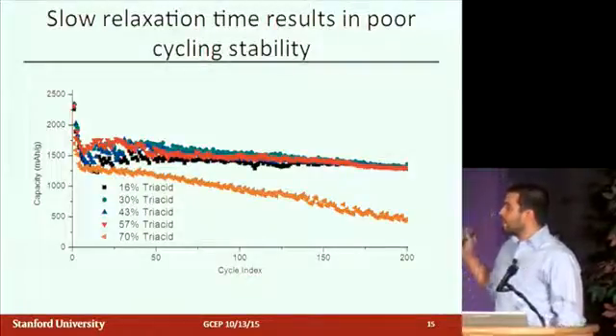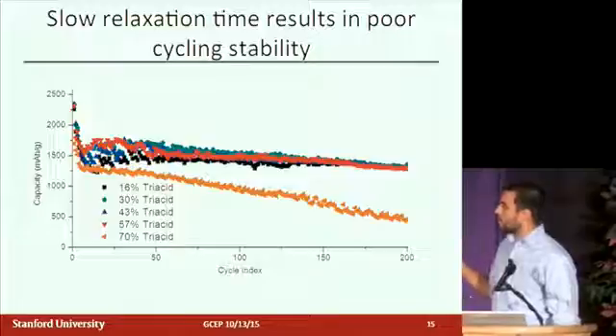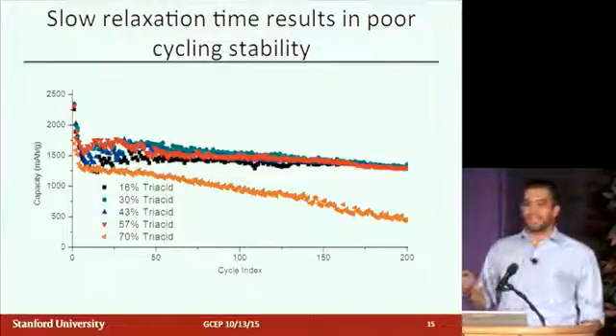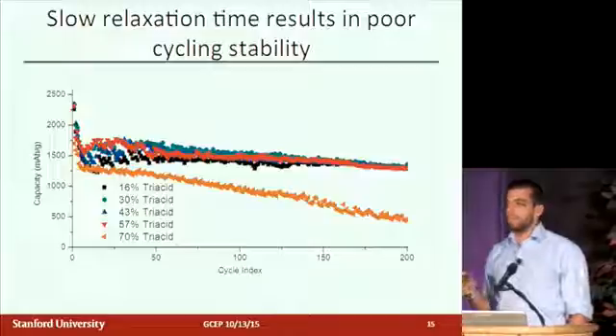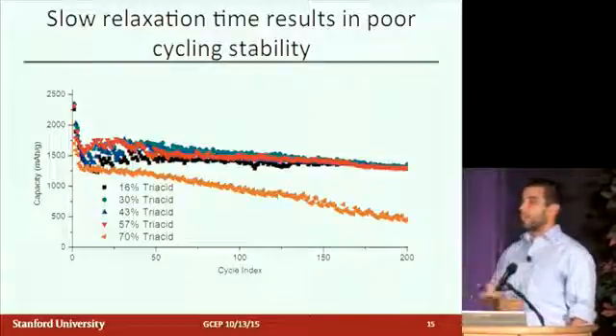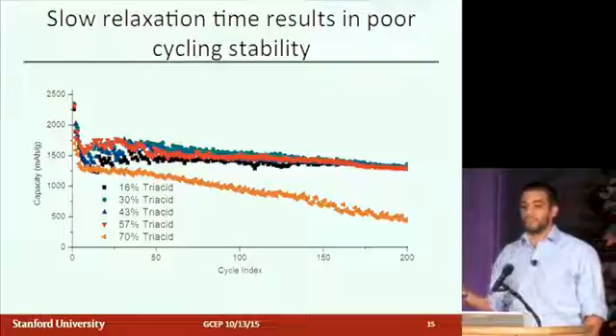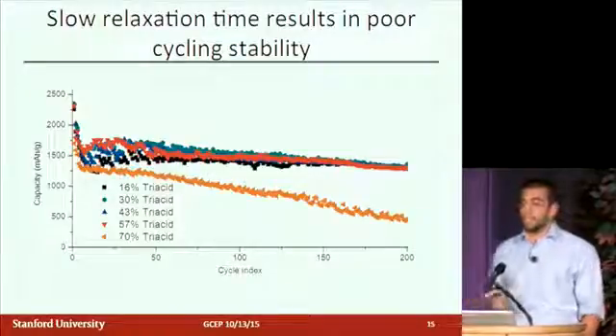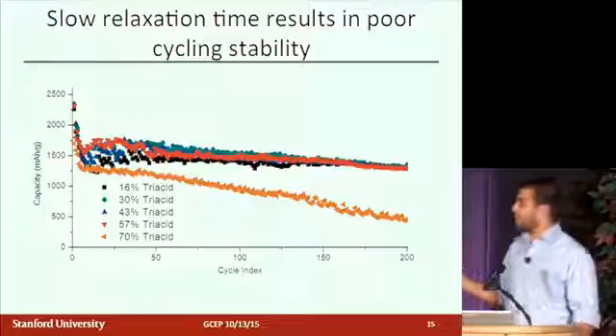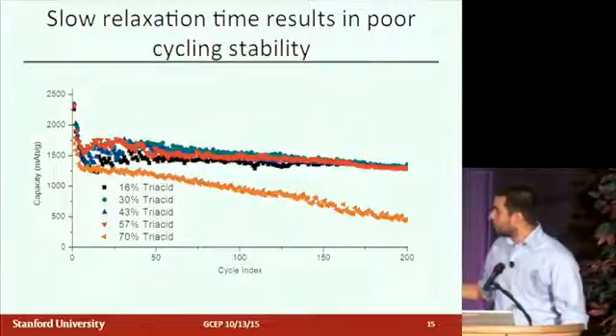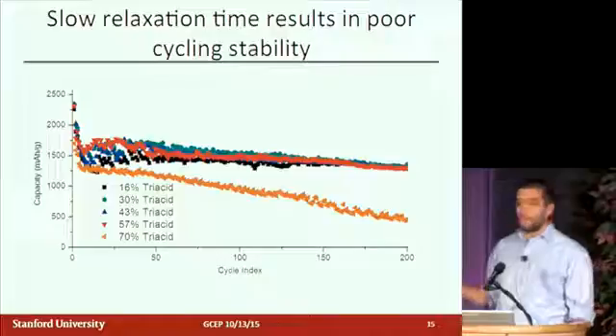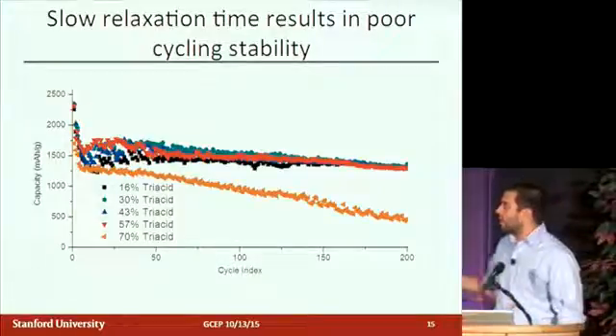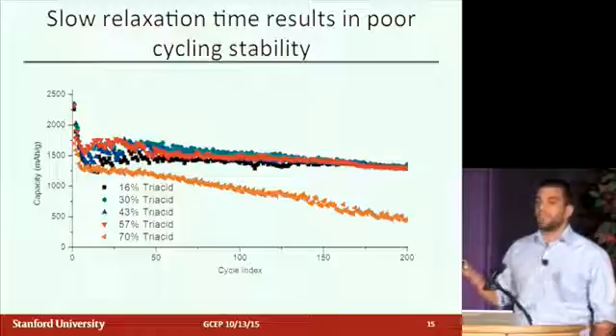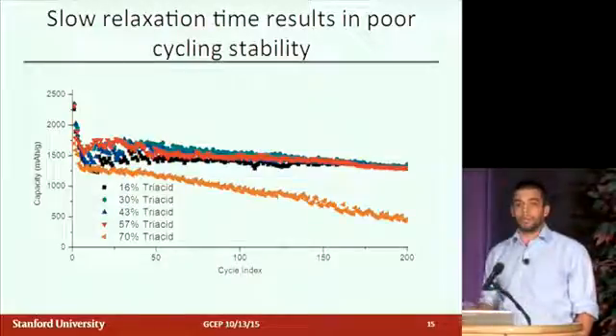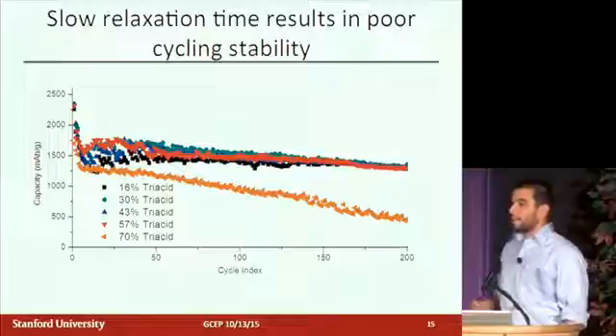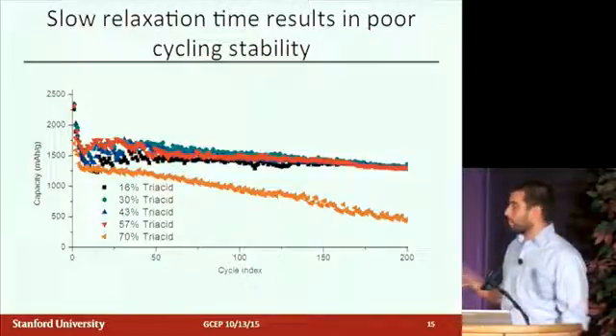So what we see is exciting for 2 different reasons. The first one is that there's almost no change, and that doesn't really sound exciting, but from an industry perspective, you're working with a material that has a really wide processing window. We can change the viscosity of this material, change how you can process it, and that doesn't change the performance in the batteries at all. We see that for the first 16% through 57% trifunctional groups in the polymer, they all cycle to about 175, 180 cycles before they reach 80% capacity, which is better, you'll remember, than the data I showed before, and also about the same.